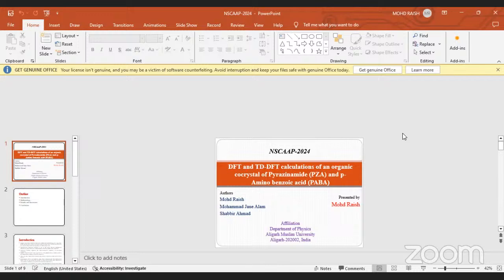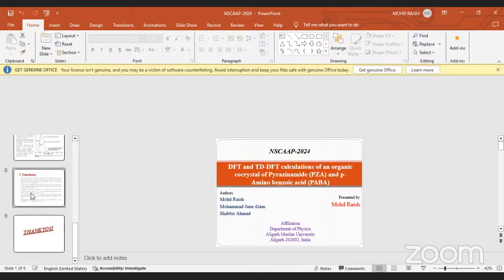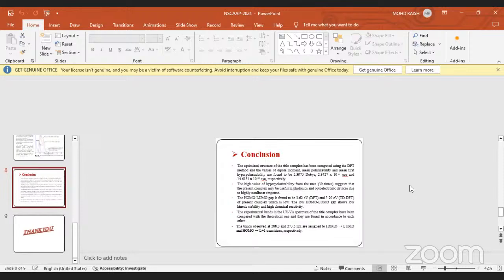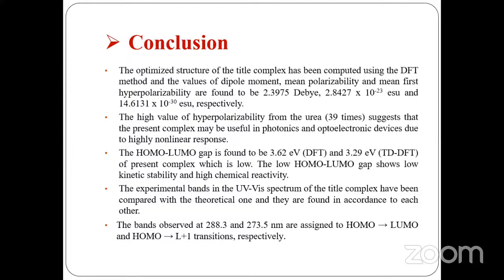Okay. Please go to the conclusion slide. Here you found the HOMO-LUMO gap by DFT is 3.62 electron volt and by TD-DFT 3.29 electron volt. How does this occur when the molecule is the same? It is possible because the DFT calculation has been done in the gaseous phase, and the TD-DFT calculation has been done in the solvent phase. So due to the solvent effect, these differences are found in the calculation.